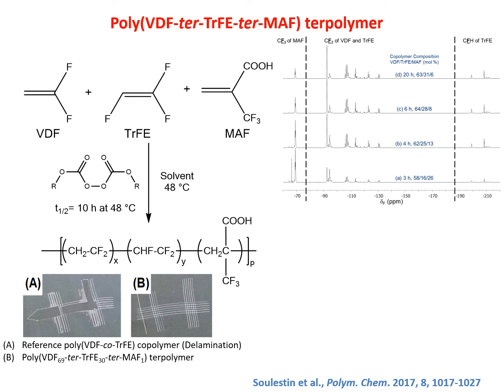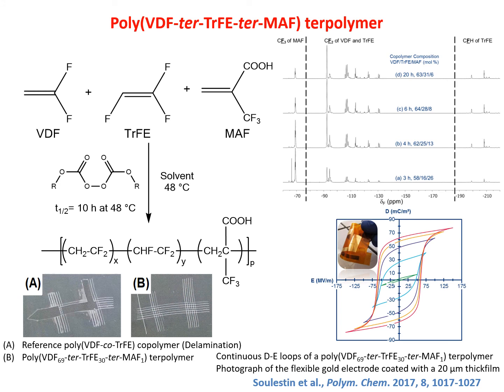These charts represent the comparison of adhesion of this terpolymer compared to that of VDF and trifluoroethylene, meaning without any MAF. You can see that here the film is peeled off in the test, while here, with a terpolymer with only 1% of MAF, you have a very good adhesion. This good adhesion enables layers of gold electrodes. As you can see here, unfortunately you don't have the piezoelectric system, but this is a ferroelectric.